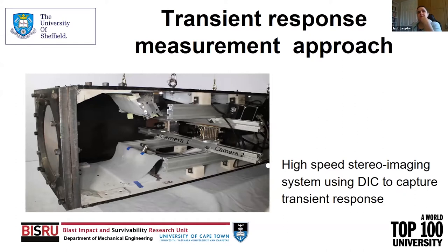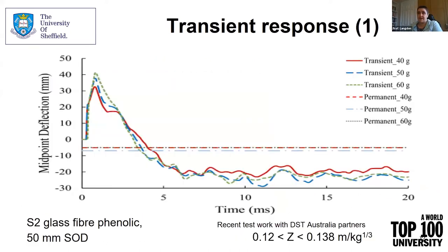The panel is speckled. So you paint it white and you speckle black speckles onto the panel. And by using DIC, you can look at the two sets of films of those speckles and identify movement of the speckled panel in those two images in each time frame, and therefore reconstruct the deformation time response of the speckled region of the panel. And that allows us to do these sorts of measurements.